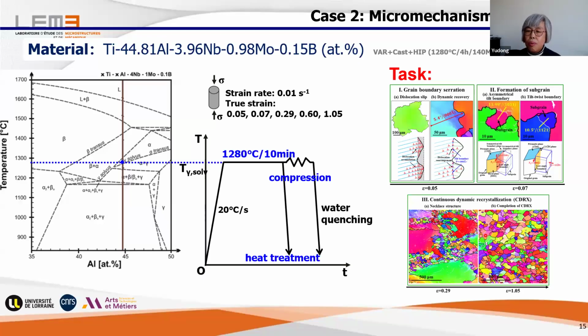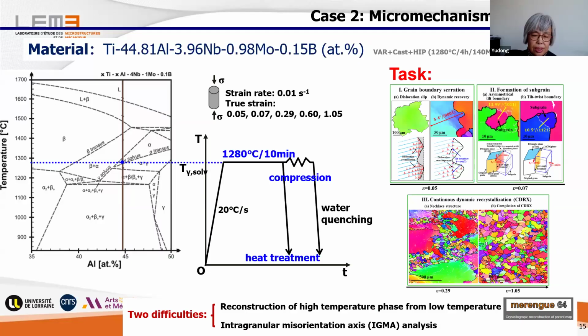We would like to know what mechanisms are behind each step. For this study, we encounter two difficulties. The first difficulty is that the single alpha phase only exists at this temperature, and we have to do the examination at room temperature. Then how do we get the information of the pure alpha phase? For this, we use a reconstruction of the high temperature phase from low temperature EBSD measurement using this MTEX Merengue software. It is also made in our lab, in our department, by colleagues Lionel Germain, Nathalie Gey, tutored by Michel Humbert.